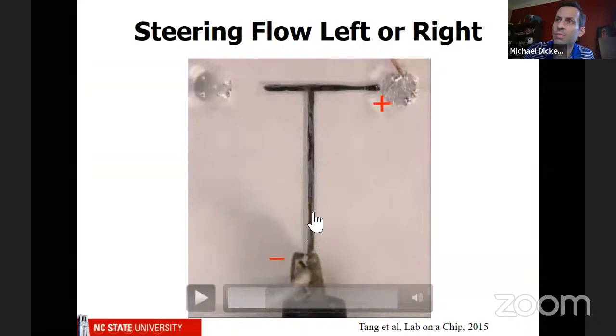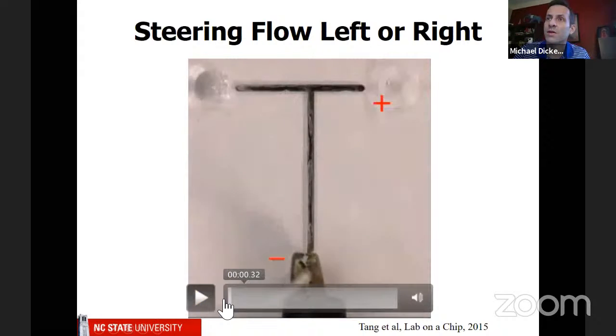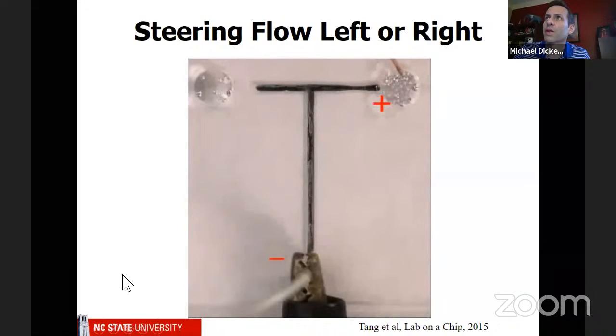This is liquid metal being pumped into a microchannel. And at the end of this channel, it has a decision to make. Do I go left or do I go right? And we're going to take a copper wire and put it into the outlet. And when we put it here, it makes the surface tension over here lower, which means it's easier for it to go to the right. So you'll see, let me start over. So you see it's going both ways. We then apply the voltage on the right, get it to go to the right, and then we switch to the left, and we can steer it in different directions.